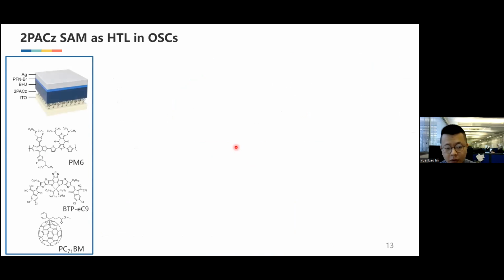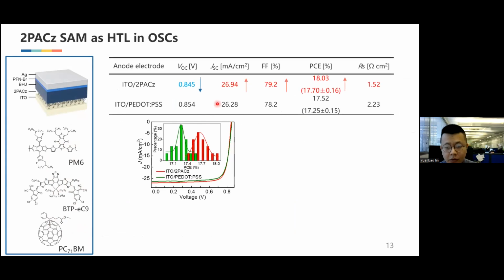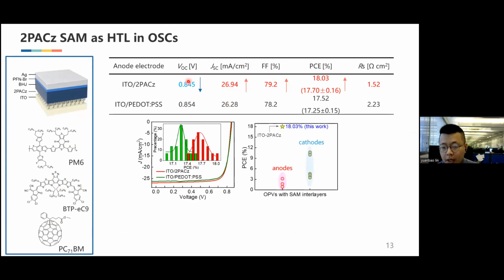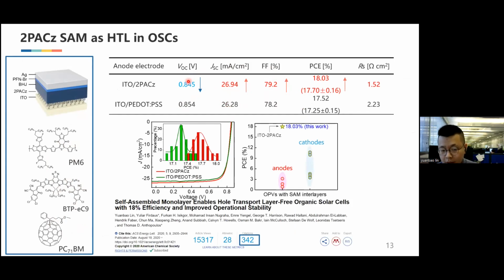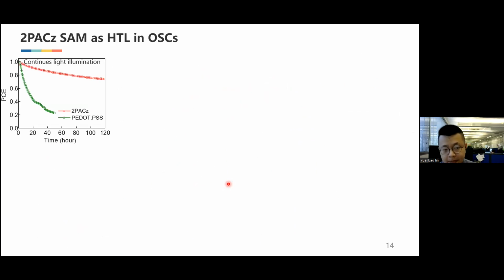In the performance, we choose another high-efficiency system like PM6:BTP-eC9 and PC71BM. As a result, the photocurrent and fill factor are slightly improved as compared to the PEDOT:PSS. In this device we can get 18% performance, but with a slightly decreased open-circuit voltage. This work was published in 2020 and has achieved over 300 citations now.